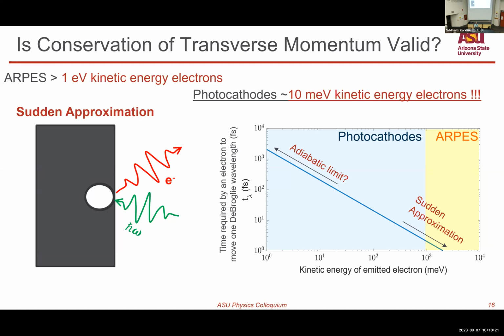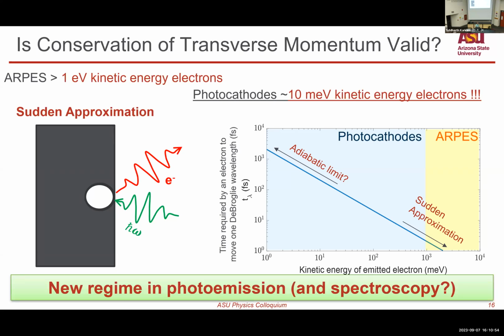And in that 100 femtoseconds, you can expect this electron, while it's getting emitted, to not only interact with the surface that's relaxing, but also with other phonons and plasmons inside the material. So whether the conservation of transverse momentum is valid at these energy scales is a very interesting question that we are trying to answer. And for the first time, we have the instrumentation, the energy analyzer that I described before, to actually measure the energy momentum distributions from such small energy electrons. And this could really lead to a new regime in photoemission physics and perhaps even photoemission spectroscopy.